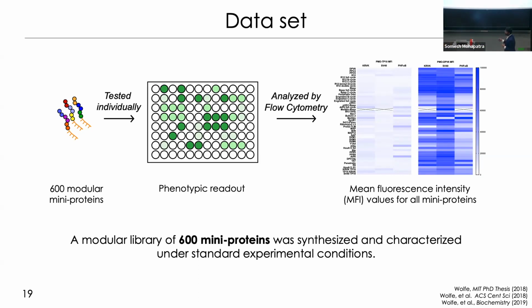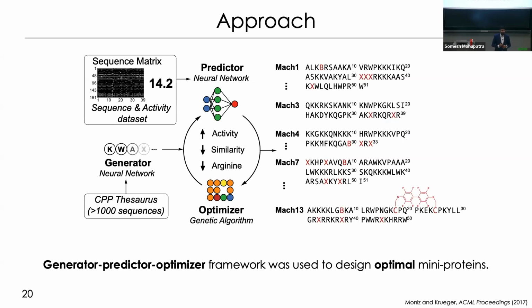On this data set, we used a generator predictor optimizer framework to design optimal mini proteins. The generator was trained and was used to generate new peptides. The predictor was trained on a fingerprint matrix representation to predict the activity. So it mapped this fingerprint matrix to the activity, and seeding sequences obtained from the generator went to the predictor optimizer loop. We increase the activity, decrease the similarity, essentially trying to get novel peptides in the process, and decrease arginine content, because arginine is known to have toxicity effects when it is injected into mice models and subsequently into humans. By using this framework, we discovered 13 unique peptides.